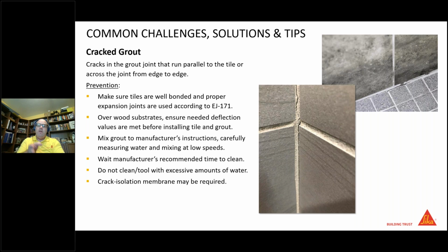but we need to follow those in accordance to that. If you look at these pictures here, both of these pictures are actually change of plane pictures. They're inside corners. One's on a floor to a wall, the other one's a wall to wall. You can see what was done wrong here. They hard grouted into it. They didn't follow the EJ 171 preparation for this, with backer rod leaving that joint free, using a sealant to allow that thermal expansion and contraction. In turn, this is what you end up with. In turn, you get a callback. And so that's what we're trying to eliminate, those callbacks, by following the proper rules of EJ 171 and making sure those tiles are well bonded.